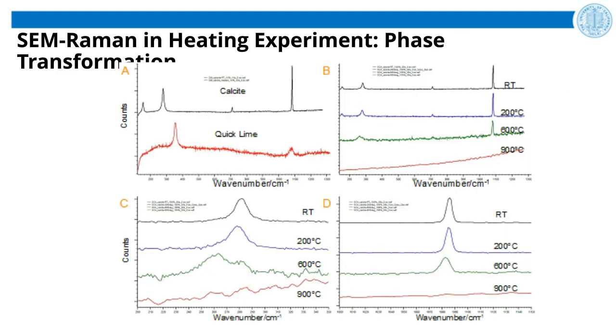The sample was slowly heated from room temperature up to 900 centigrade. On A, we can see Raman spectra of the crystal before and after transformation, and B, C, D show Raman spectra of the crystal during the in situ heating experiment. On slide B, we can see characteristic calcite peaks at 153, 280, 711, and 1085.